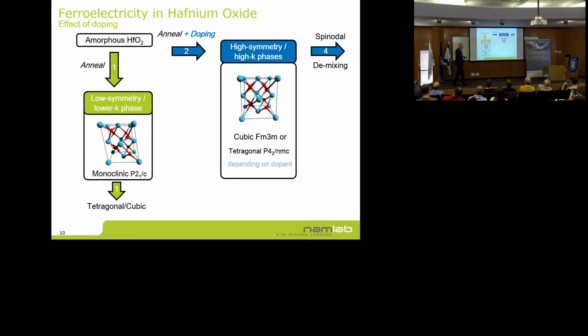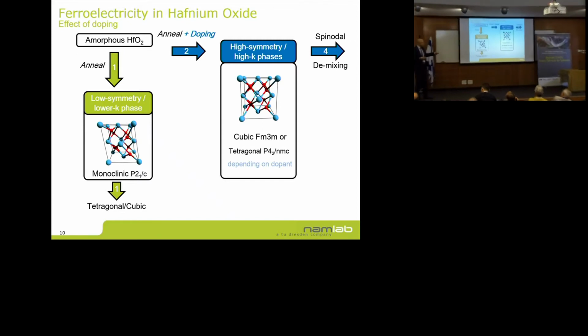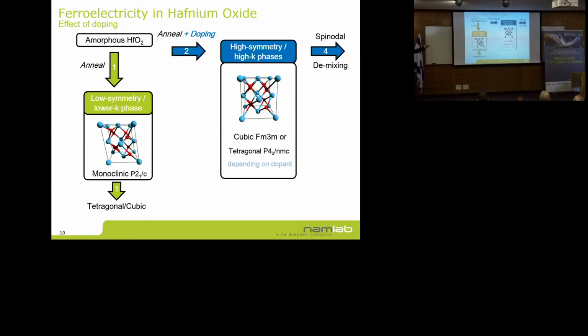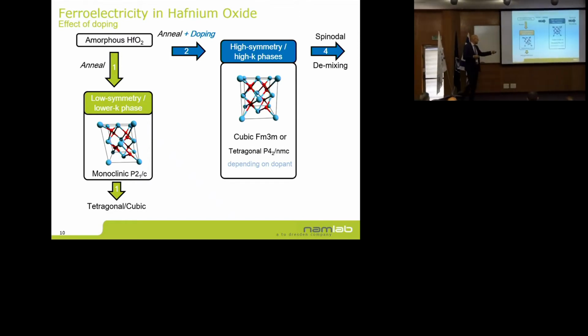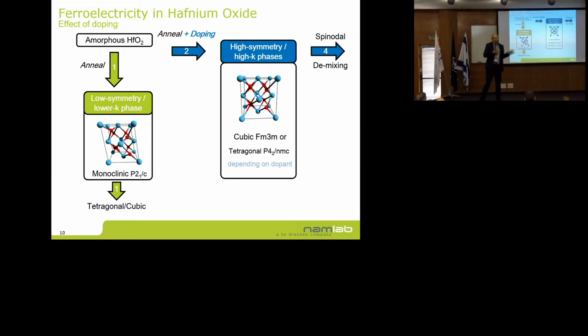We know how to tailor ferroelectricity in hafnium oxide. Now the question is, why at all is hafnium oxide ferroelectric? This all came as a surprise to us. It is well known that there is an orthorhombic, non-centrosymmetric phase in hafnium oxide, but normally you only get that under extreme conditions of very high pressure. Normally you get a monoclinic phase in hafnium oxide if you do annealing. You can stabilize higher symmetry phases like tetragonal or cubic phases if you add dopants.